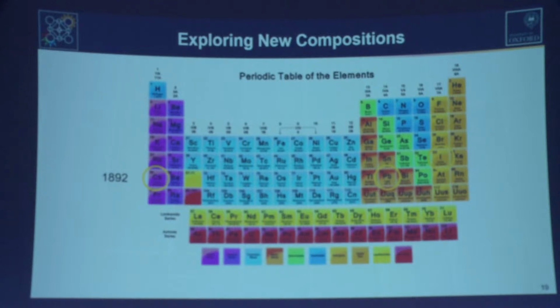So we actually have to go off the periodic table and use organic cations. This is an organic ammonium cation called methylammonium. This was actually reported in 1978 as a material, methylammonium lead triiodide, and this is one of the materials that Miyasaka and Kojima used first in their first devices. This was pretty much the material we started using, though we put in a little bit of chlorine.